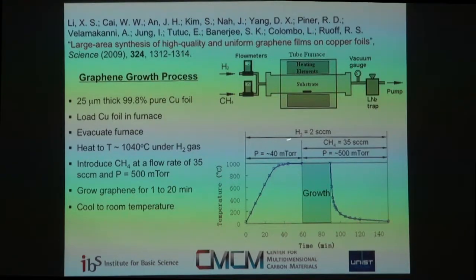And so one method that has been very productive has been copper foils. And that led us to invent some approaches that have also been very useful, I think very useful for the community. And so, being somewhat inexperienced, we went way overkill here. We had an hour of exposure to hydrogen at temperature around 1,000 degrees C, 1040. In reality, we now know from our colleagues that probably 30 seconds is enough to remove the oxide layer on the copper, the native oxide layer, and then expose to a hydrocarbon like methane.